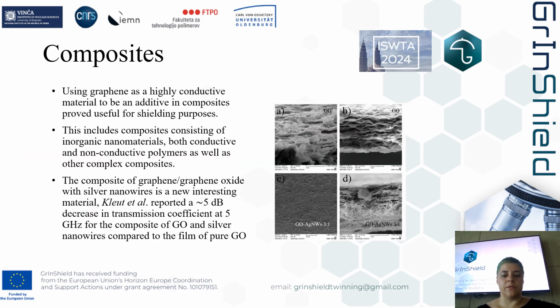And these are the composite materials that we created using graphene and silver nanowires in our aim to produce the best possible material to have the highest level of electromagnetic shielding. We are planning to create both composites of inorganic and organic materials with graphene, and this is one of the materials that we already published research on, consisting of graphene oxide and silver nanowires, and we reported about 5 decibel decrease in transmission coefficient at about 5 gigahertz for this kind of composite.